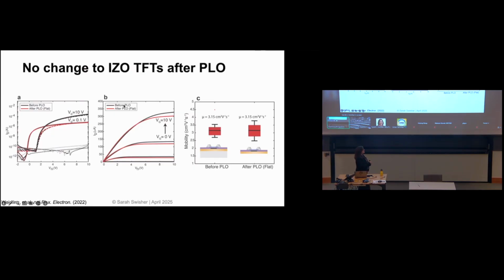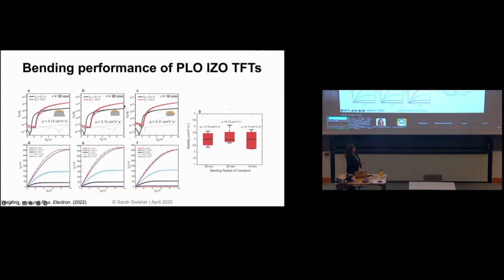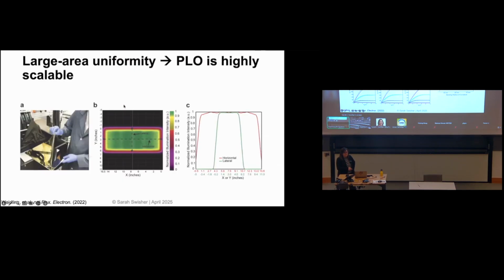So as I noted, it's a little bit lower because we use that lower temperature here. But when you look at the statistical difference between the mobility before and after the PLO, there is no difference. So what this is saying is that the fact that it reaches about 120 degrees right there at that interface is not changing these devices. And then we did some bending tests and showed that they're robust to bending around these different radii, which is great. So we have these nice flexible TFTs that we were able to fabricate using that glass carrier.